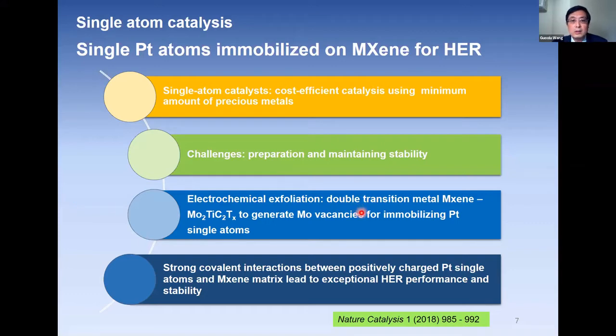So in our work, we successfully used the electrochemical exfoliation method. Here we use a double transition metal MXene, molybdenum 2 titanium carbon 2, to generate molybdenum vacancies for immobilizing platinum single atoms. And when we deposit the platinum single atoms on the MXene surface, the strong covalent interactions between the positively charged platinum single atoms and the MXene matrix lead to exceptional hydrogen evolution reaction performance and stability.